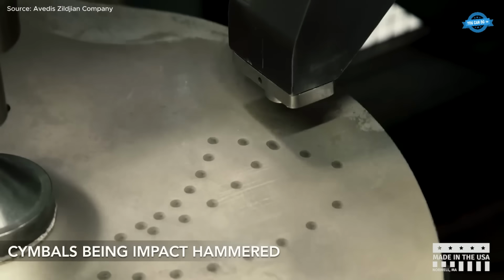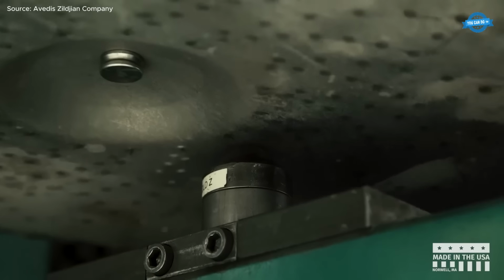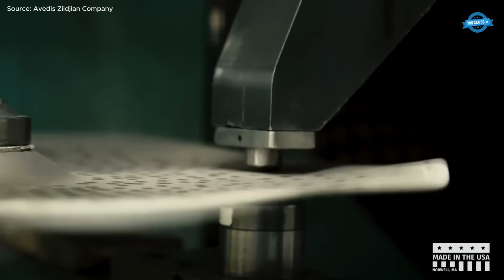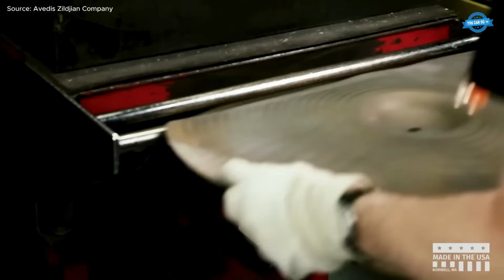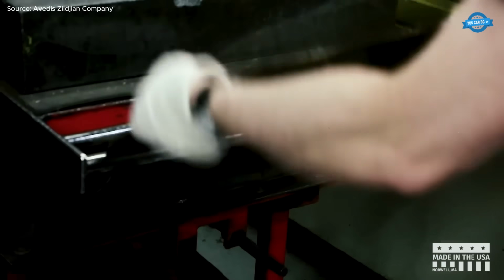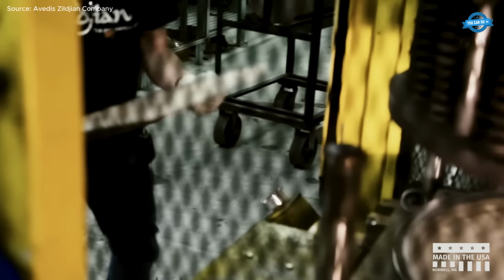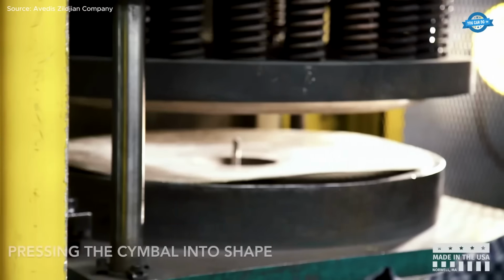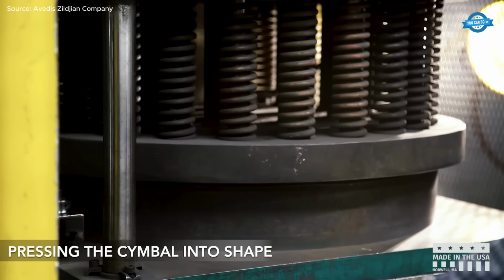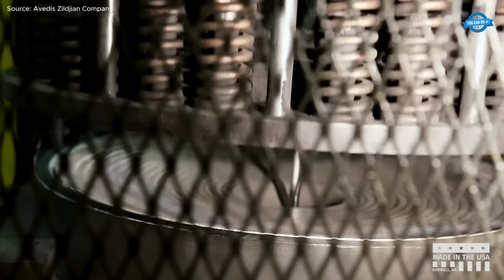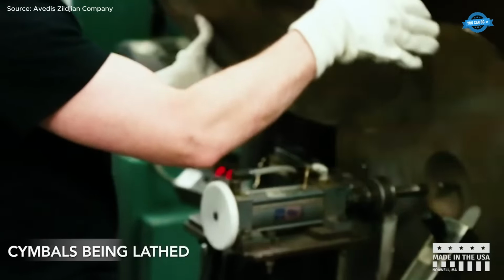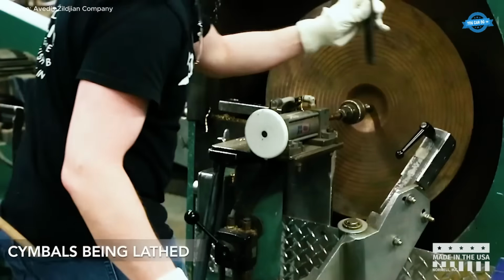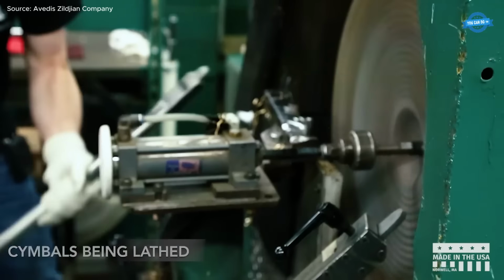Acoustic character begins to emerge during hammering. Rotary and impact hammering systems apply controlled patterns across the cymbal surface, redistributing internal stresses and shaping tonal characteristics such as sustain, pitch complexity, and projection. The cymbal is then placed in specialized die presses that apply up to 80 to 90 tons of pressure to establish the final curvature and taper profile.